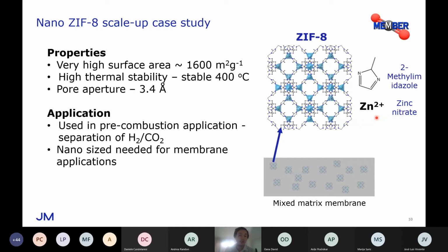In the MEMBER project, we're using this MOF for a pre-combustion application, so the separation of hydrogen from CO2. The reason that we need to make nano-sized, nanoparticle-sized materials for this is that they will be incorporated into a polymeric membrane to make a mixed matrix membrane. If the particles are too big, then they can protrude from the surface and cause defects in the membrane, allowing gas to bypass through that membrane, reducing the selectivity of that membrane.